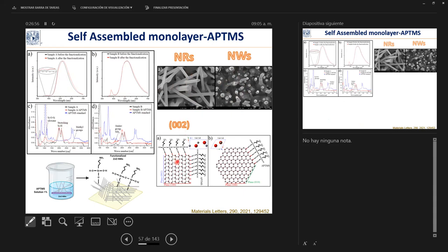What was the reason? We found that these nanorods grow in a particular orientation, that is 0, 0, 2. When the nanorods grow in this orientation, they have more polar surfaces. As you can see in this image, this is a schematic we proposed. When the nanorods grow in 0, 0, 2, they have two different sites where the interaction can happen. As I mentioned before, in zinc oxide, we have zinc and oxygen defects. So nanorods have more exposed oxygen defects. Whenever some analyte comes, it finds more sites to have the bonding in the case of nanorods, whereas in the nanowires, we have only one interaction site.